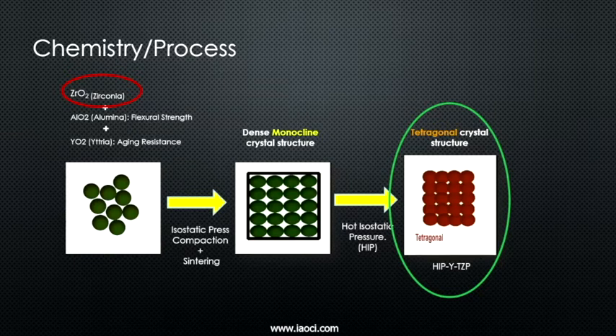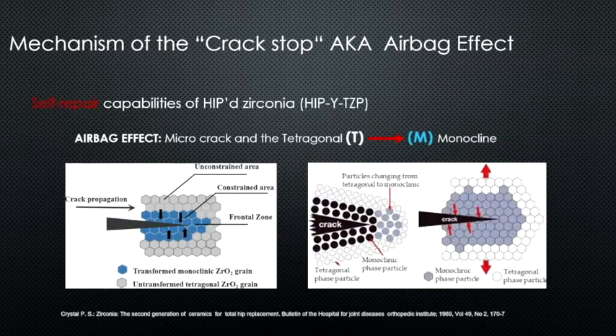Now, one thing you'll notice here is the particles are much more open here than here. That's the difference between something that's prone to crack and something that's less prone to crack. Because for a crack to take place and propagate, just like it shows here.